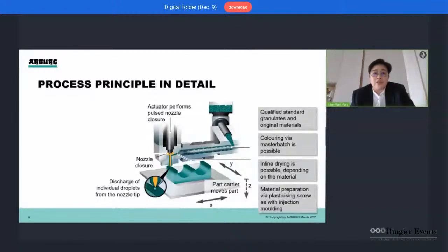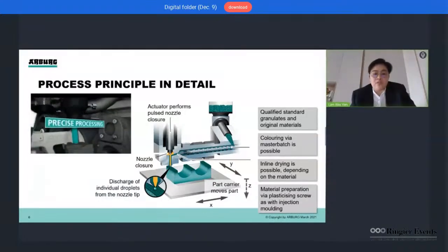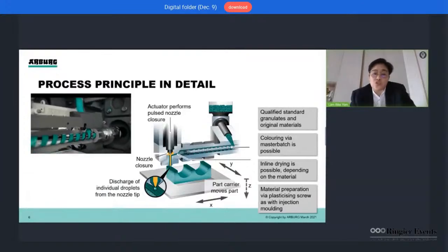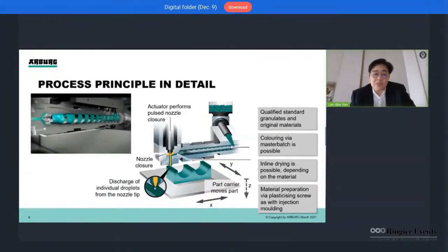The short video actually illustrates most of our process and what we can do. To further explain, plastic free-forming, which is the method used here, is an extrusion-based manufacturing technology. In the material preparation unit, the pellets or granulates are plasticized with a 15 millimeter rotating screw in a heated barrel, just like injection molding.